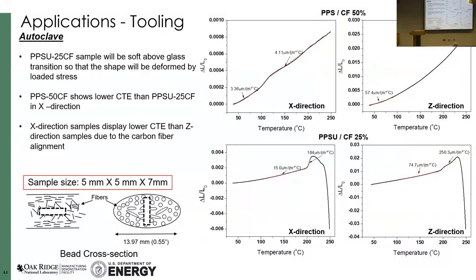So now for tooling, CTE is very important. After we fixed all of these viscosity problems, we printed, but we need to understand the CTE of the tool, the coefficient of thermal expansion, because as soon as you put it in an oven or an autoclave, it is no longer the same dimensions. It will just grow, right? And your composite parts that you are molding on it is completely off. So we need to understand that. So how do you measure CTE? Using a method called TMA, right?